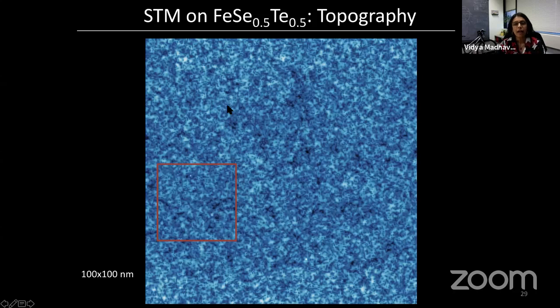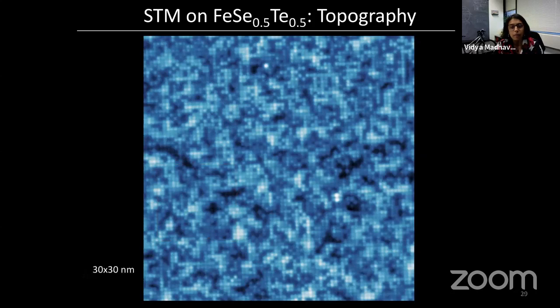So if you look at a large scale topography, if you have nice crystals, then the topography looks like this. You can zoom in and you can see a square lattice. And all of this inhomogeneity comes from the fact that this is an alloy, an almost 50-50 selenium-tellurium substituted alloy. So the dark and the bright represent selenium and tellurium atoms.